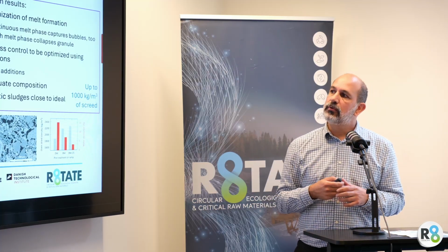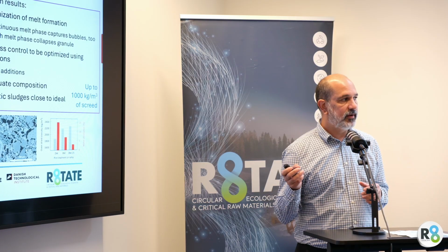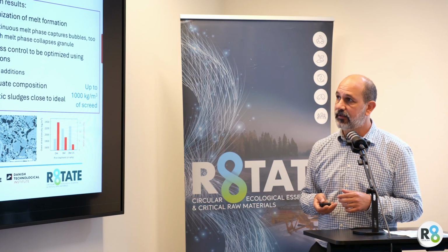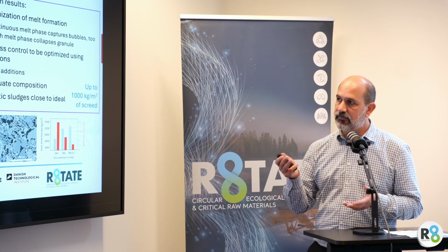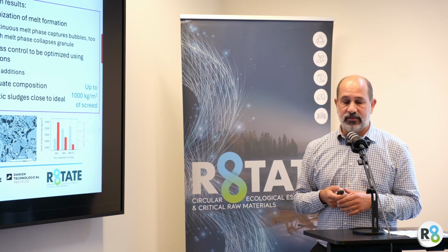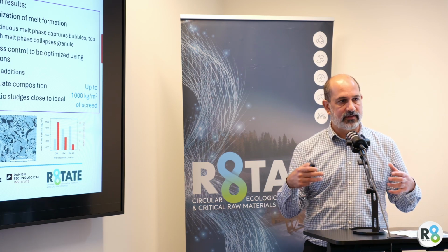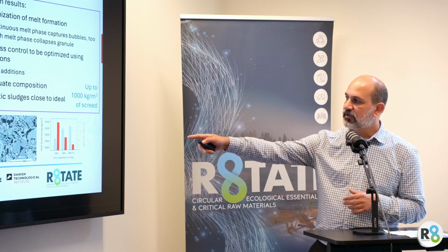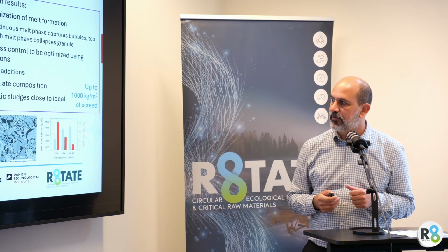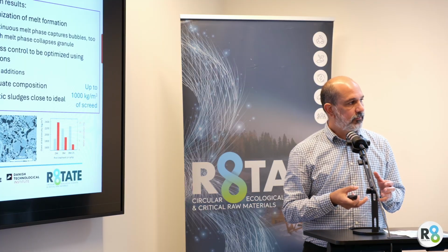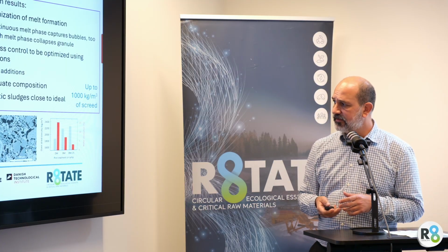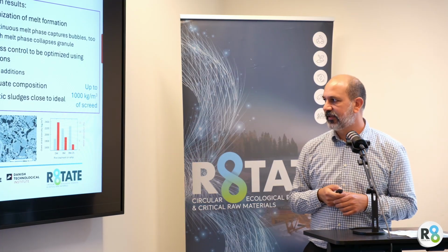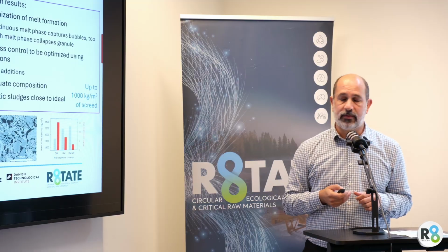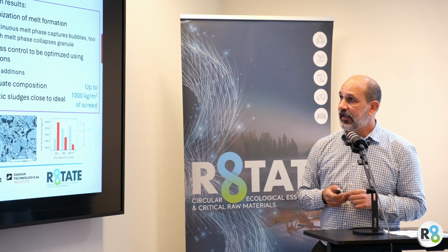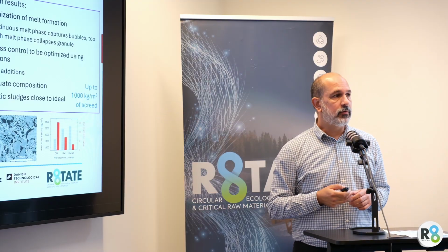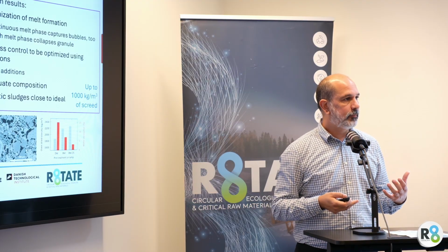Again, we had to correct a little bit the chemistry and mineralogy of this original sludge by adding some mineral additives, 10 to 20%. But we succeeded in the design of these particles that need to be very porous internally. So you need to have a good microstructure that connects all the particles, but at the same time you need to have these bubbles embedded in the material. Here you can see a correlation between the density and the water absorption, which is a proxy for the porosity of the material. For this material, we are able to incorporate it up to 1,000 kilograms per cubic meter of